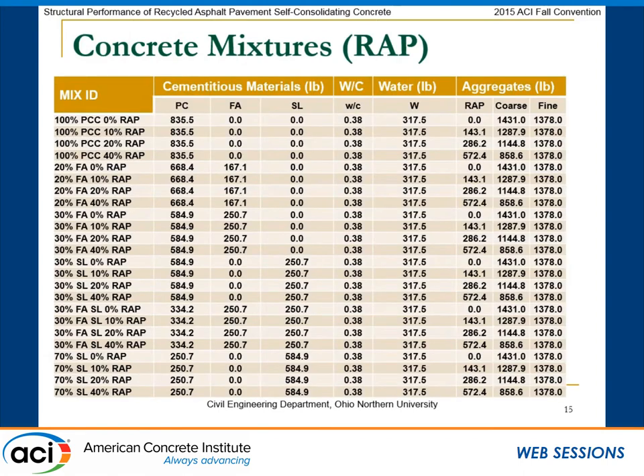So here in this table, this summarizes all of the 24 concrete mixtures that were used in this study. So the RAP content ranges from 0% to 40%. And we have used 100% Portland cement for some of the mixes. Some others we used 20% fly ash, 80% Portland cement. And some others we used 30% fly ash, 70% Portland cement. Some others we used 30% slag, 70% Portland cement. Some others we used 30% fly ash, 30% slag, and 40% Portland cement. And last we used 70% slag, 30% Portland cement, and again, the RAP content ranges from 0 to 40%. And here, as you can see, the water to cement ratio was constant, and it was 0.38.